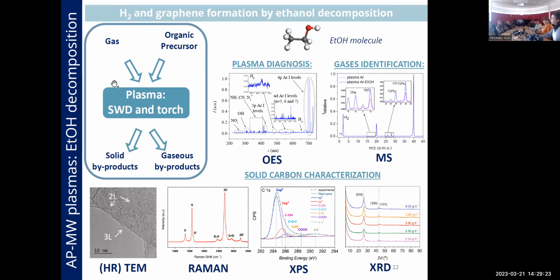Then what we do is characterize our plasma by optical emission spectroscopy. After that, we need to control which gaseous byproducts we are obtaining from the decomposition of ethanol by mass spectrometry. Then we will realize if we are producing hydrogen, in which way, and if ethanol molecules are completely decomposed or not. After that, since under certain experimental conditions we have solid carbon formation, we analyze this solid carbon with high resolution transmission electron microscopy, Raman spectroscopy, X-ray photoelectron spectroscopy, and also X-ray diffraction.